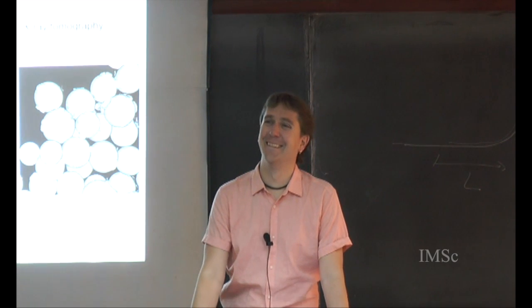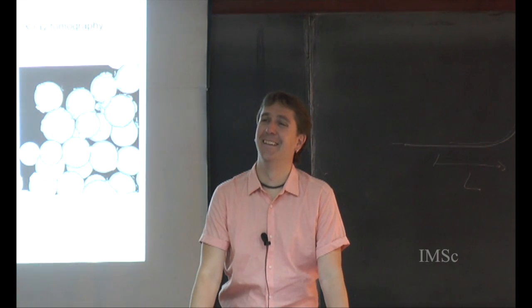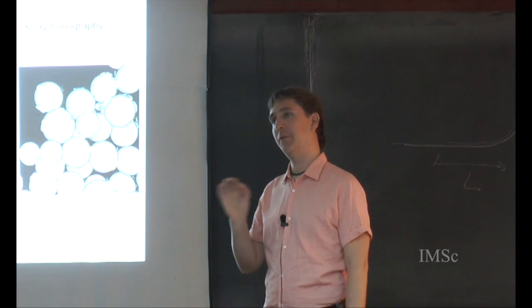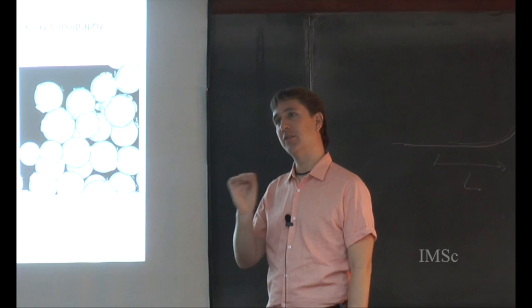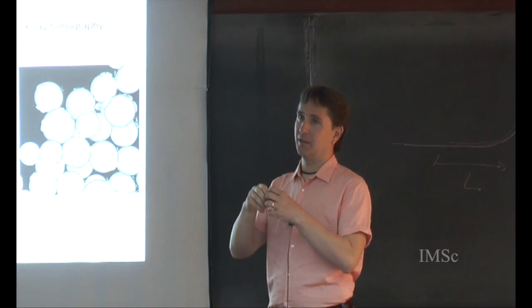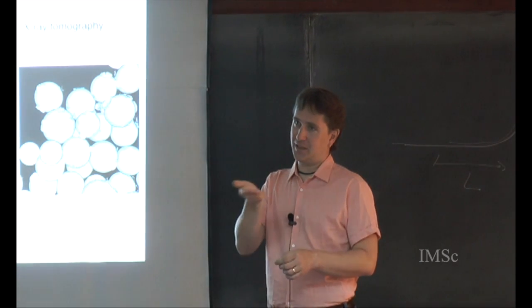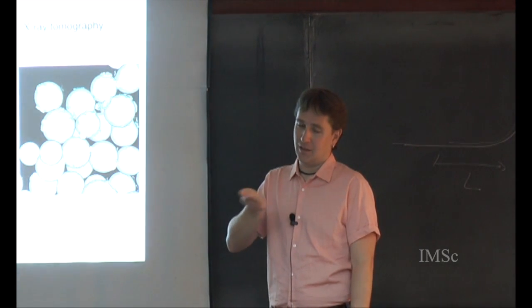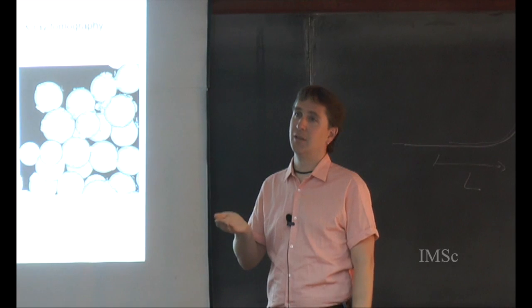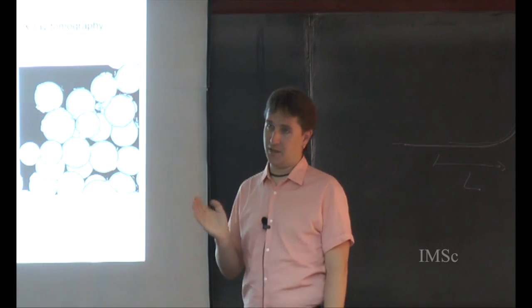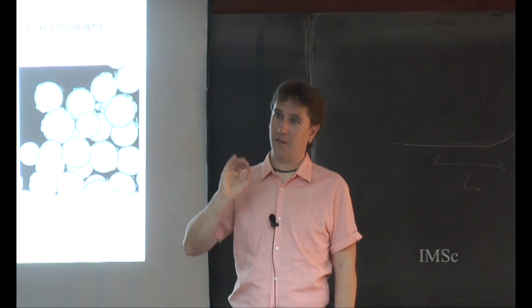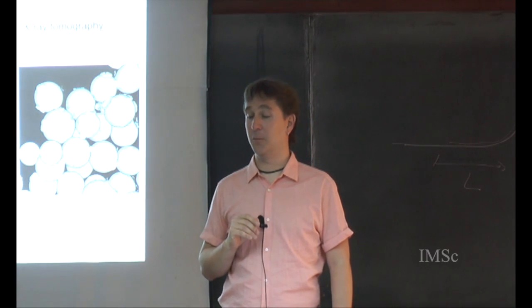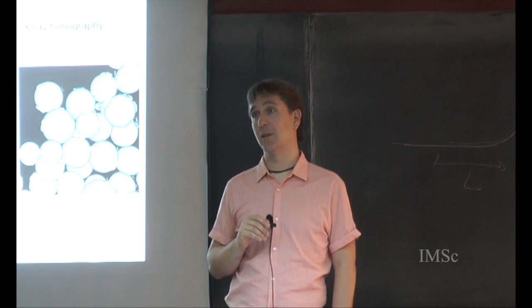Maybe shaking or something? Shaking it is actually challenging, because even with a wet granulate, there's a large energy barrier to breaking the liquid and reforming it. So shaking a sandcastle, which behaves as a paste, requires a finite yield stress in order to fluidize the material. So it's not quite as easy as just shaking a normal granulate. You require finite stress before it fluidizes. So it could be done. It's not something that we pursued, though.